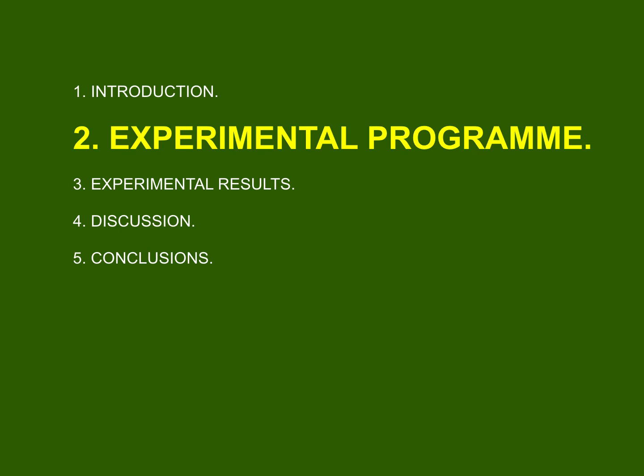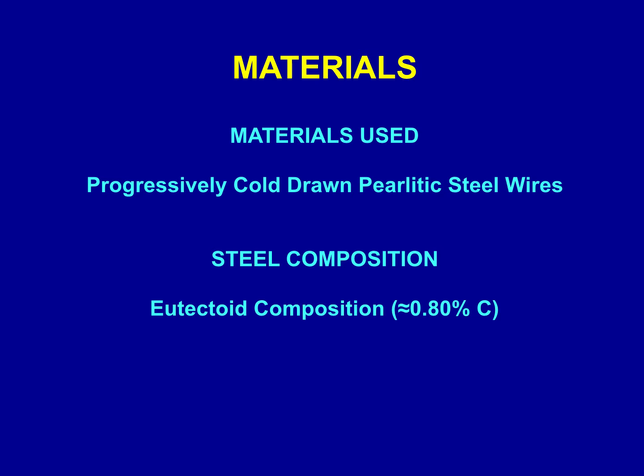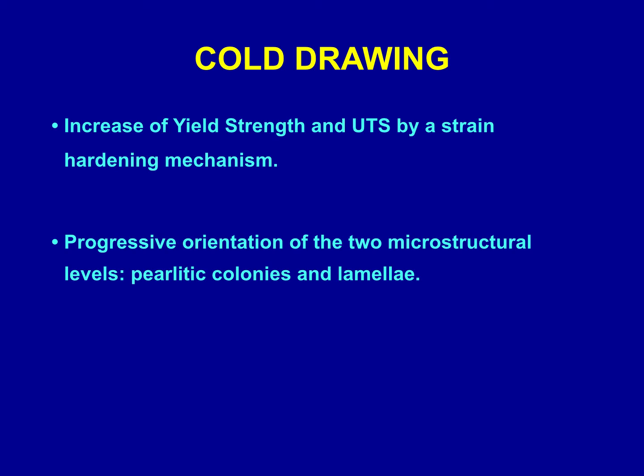The experimental program. Materials used: progressively cold-drawn pearlitic steel wires. The steel composition: eutectoid composition, roughly speaking 0.80% of carbon. Cold drawing consists of an increase of yield strength and ultimate tensile strength by a strain hardening mechanism, with progressive orientation of the 2 basic microstructural levels of pearlitic colonies and lamella.